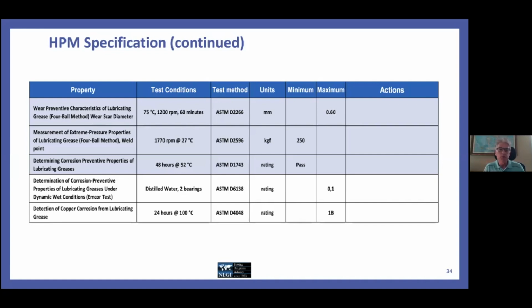The next one is corrosion preventive properties, the standard static rust test in distilled water, with standard conditions, and a minimum pass, which is the same as we have in GCLB today, so nothing new there. You can't really do anything with that test to make it more severe, either in limits or in test conditions, because it's a pass-fail test, and those are the specified test conditions in the method.